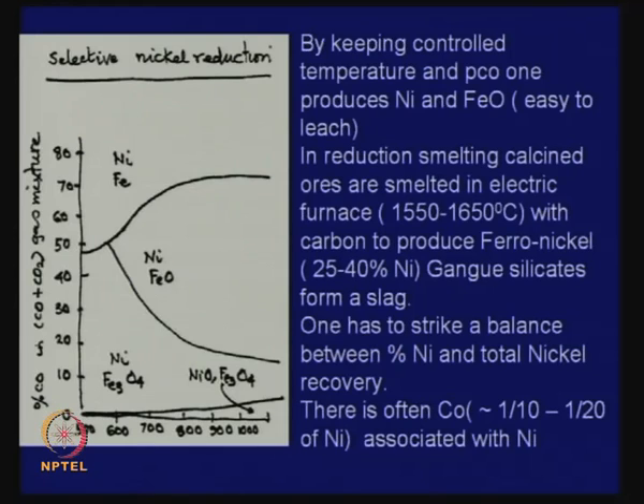For that we have to go for electrolysis, by decomposing nickel carbonate into nickel oxide, dissolving in an acid solution, and electrolysis. It may not be necessary. If it is for alloying, if you add nickel carbonate, it will decompose very easily. So, we have to keep in mind what it is that we want. If you want ferronickel, we have to go for smelting, but we can also produce elemental nickel by initial reduction roasting followed by leaching of nickel. Now, this sort of work has been done in India, and in the next lecture I will come back to this subject and give you a little more data and discuss it more thoroughly.